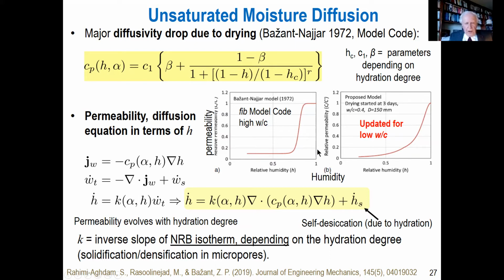Now, for modern concretes, we have many more data now with better humidity gauges, piezoelectric gauges. We conclude by the same reasoning that this formula does not need to change the form, but needs to change the parameters somewhat. Beta and R have to change. It gives a curve like shown, the red one, which decreases more steeply. It goes about 50 times down here and surely goes to zero, because when concrete is fully dried, it has no water in it, there is no permeability either, but it also does not creep.